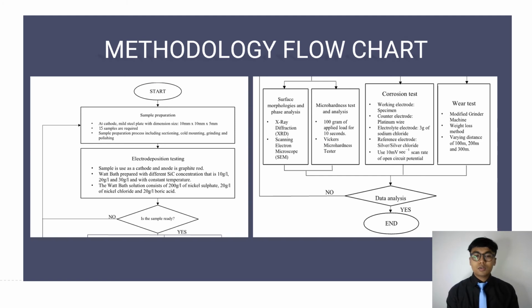The counter electrode was platinum wire, the reference electrode was silver/silver chloride, and the working electrode was the samples. All the electrodes were submerged in a 3 gram sodium chloride electrolyte solution. The current supply flowing through the counter electrode was then measured and the data was analyzed. Following that, the Tafel polarization test was performed at a 10 mV per second scanning rate.